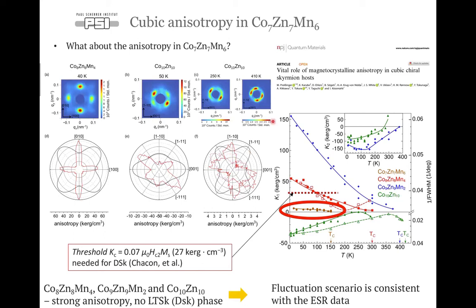And the same is also suggested in the recent ESR data published in this paper by Eastern Cache Market Group. In this report, they have measured magnetocrystalline anisotropies K1 and K2 for cobalt zinc manganese single crystals with different compositions: 776, 884, 992, and 1010. And they have shown that really strong magnetic anisotropy may be observed in 992 or 1010 materials, but in 776, the K1 constant is really low compared to these previous two materials.